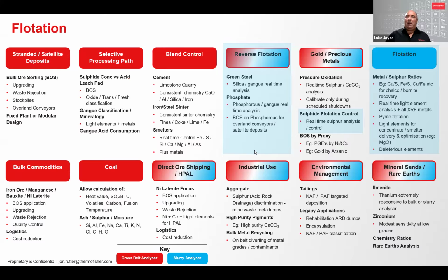Light elements associated with clay and talc or relating to acid neutralization can be measured and therefore better controlled. PG&A can also add value in reverse flotation, for example, in phosphate and in iron ore. In iron ore, it enables real-time control for producing low silica concentrate for pellet production used in producing green steel.